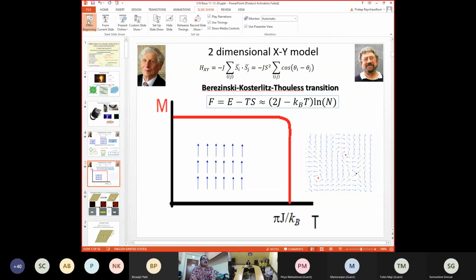So now, if you are at low temperature, and you try to create a topological defect, since this prefactor is positive, and here you have log n, which is the logarithm of the system size, you have a large increase in the free energy. Therefore, it's energetically completely unfavorable to create a vortex at low temperature. However, when I cross the temperature 2J by kB, this prefactor becomes negative. Now, if I create a vortex, I will have a very large decrease in the free energy. So it will become entropically favorable to create these vortices. The free energy will decrease as soon as I create the vortex.